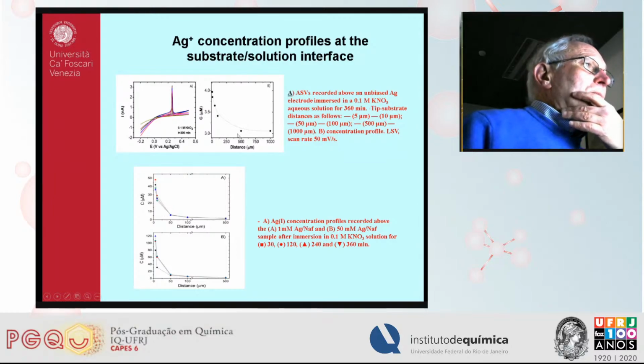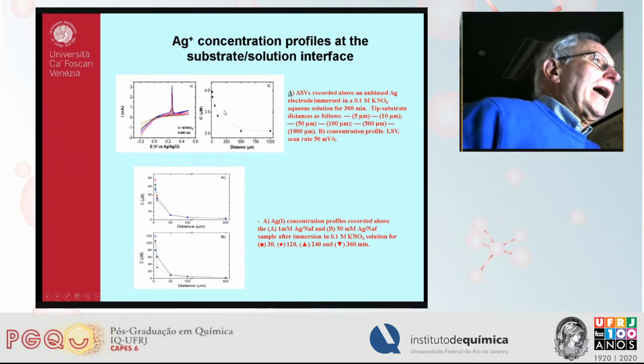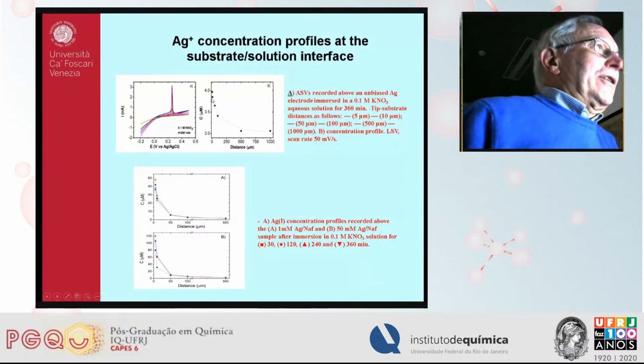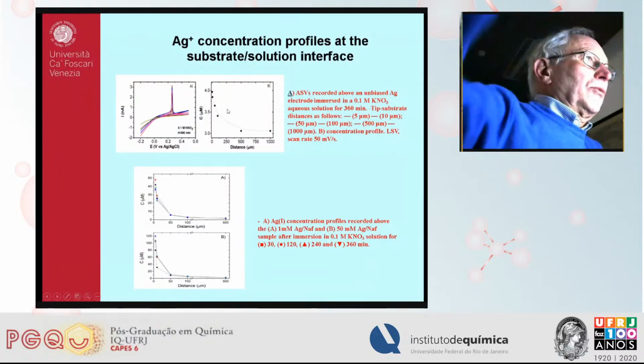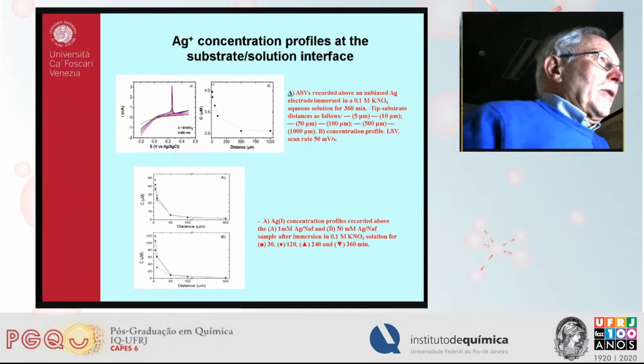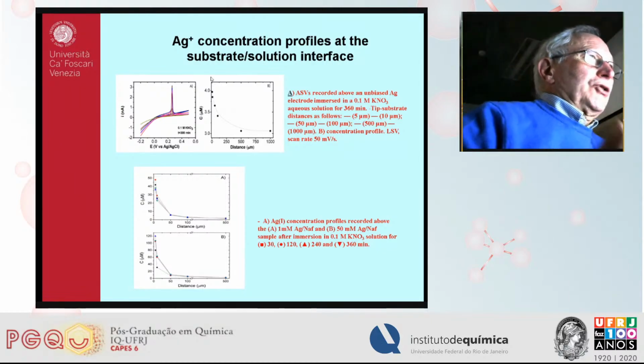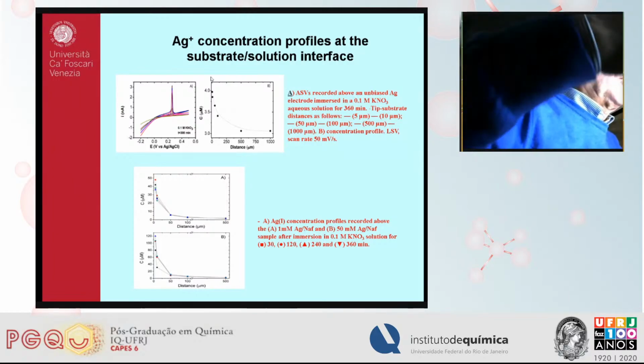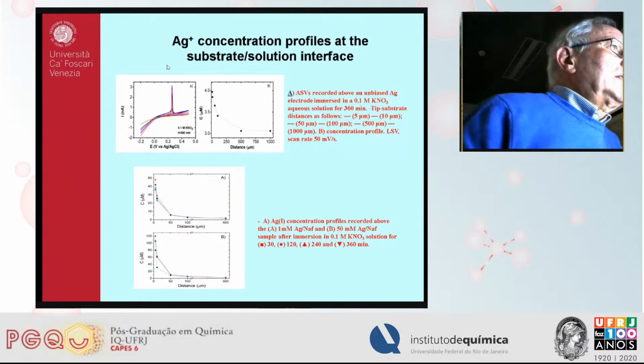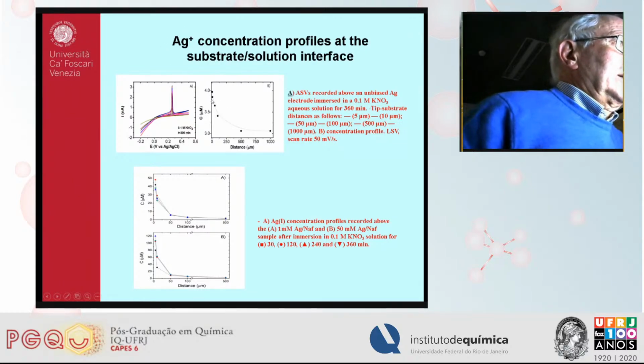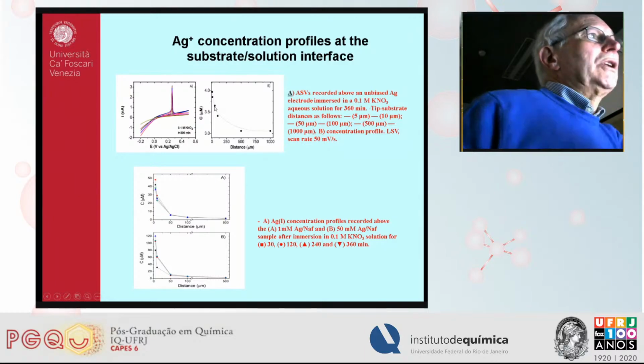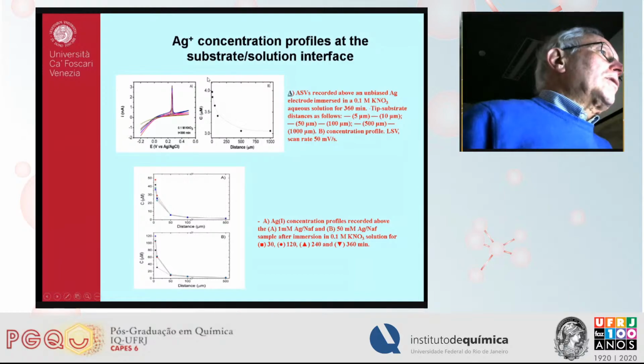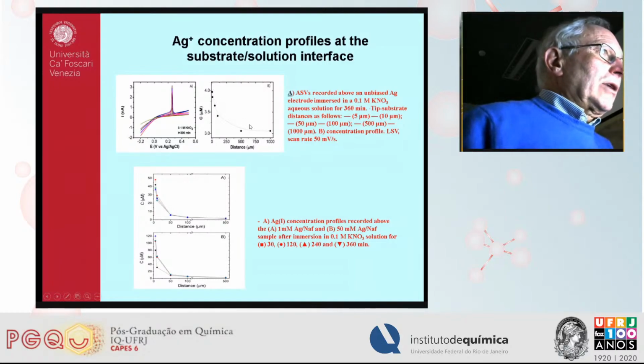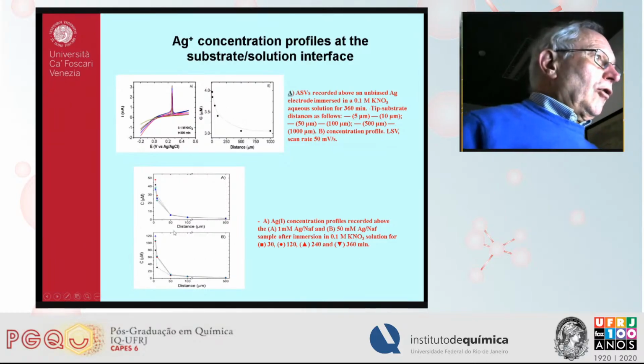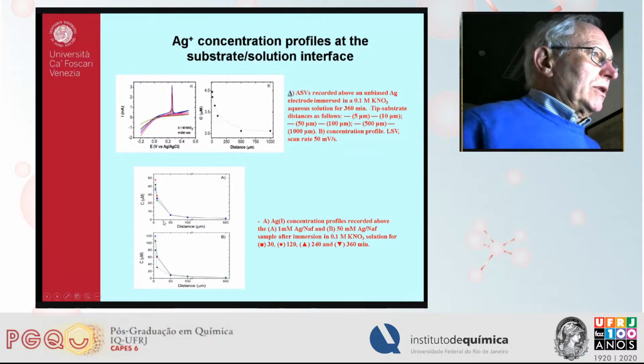This is an important result, which means this trend suggests up to which distance silver ions can act when in contact with the medium, with the solution. Or, for instance, if there is a food packaging which is more or less closer to the food, it can act differently depending on the amount of silver ion able to reach the food itself. Okay, so in other words, we can establish the concentration profiles at a given time, or how this concentration profile changes with time.